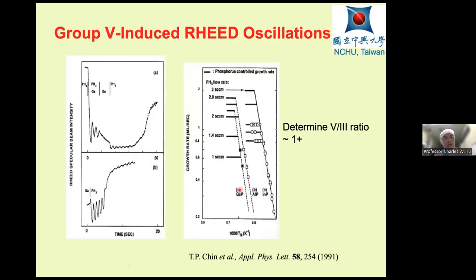We can also grow gallium phosphide. So we have gallium and we have thermally cracked phosphine into P2. When we open the gallium shutter, we see this oscillation determined by gallium. Then we stop gallium and close the phosphorus shutter. We deposit gallium and the surface becomes rough. After maybe 10 monolayers of gallium, we open the phosphorus and we see this oscillation again, meaning that we have excess gallium on the surface. Since the surface is hot, atoms move around, and now with phosphorus coming in, we form monolayer high islands. Again, we grow this gallium phosphide layer by layer.